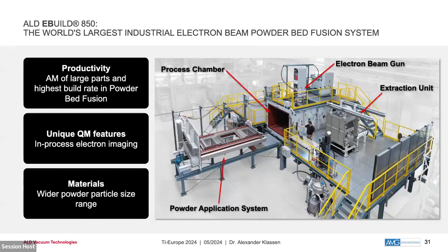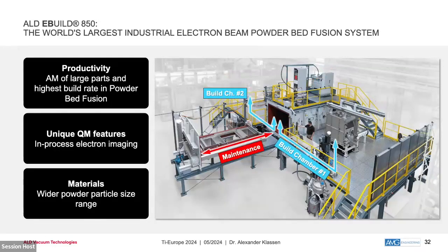This is just to give you an idea about the moving directions. This is just for maintenance reasons. You can remove the powder supply from the machine. But the more exciting one is this one, where you can detach the build chamber from your vacuum chamber, so that you can move your build away from the machine, process it, remove the powder and the parts, and in parallel use a second build chamber so that you have reduced downtime of your machine.